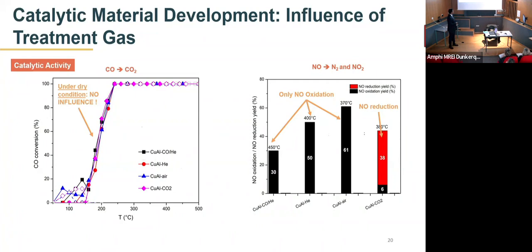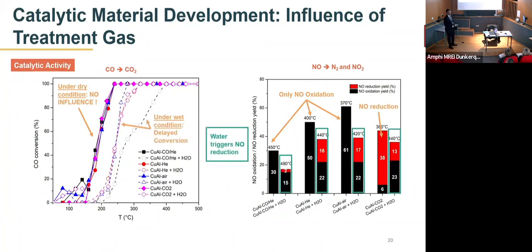When we look at the wet reaction conditions, in the CO conversion values we see that there is a delay in the CO conversion, which is generally associated with the competition for the common active sites between the reactant molecules and the water molecules. On the other hand, in the NO conversion activity, we see some NO reduction yield for all the samples. Here we can conclude that the water triggers NO reduction, which could be because of the occurrence of a water gas shift-like reaction.